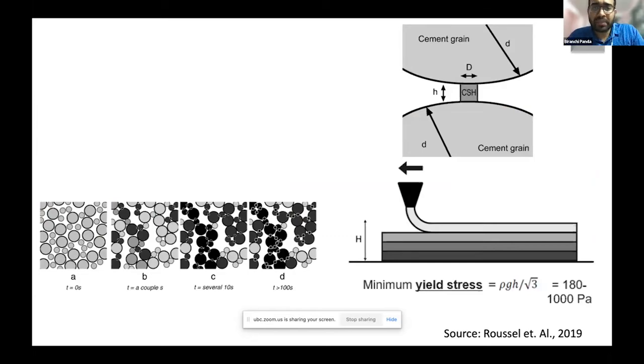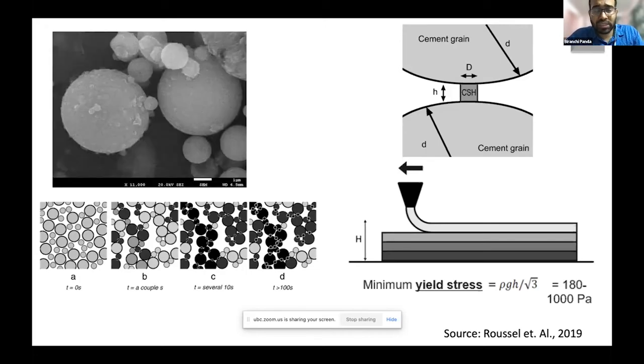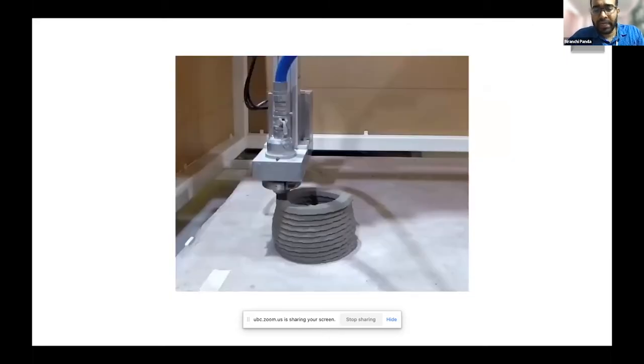Having said that, when we have cement, the ordinary Portland cement, which is most commonly used everywhere these days, in India especially, you don't see any problem because we get some inherent thixotropy because of the cement particles. But if we want to promote sustainable materials like fly ash and industry waste like slag, so recently we are working with two or three different companies who are providing us this kind of industrial byproducts, and we are trying to use them in the material formulation. So we see many challenges. For example, if you take fly ash, due to its spherical shape, we are not getting proper buildability, and therefore we have used some kind of nano materials.